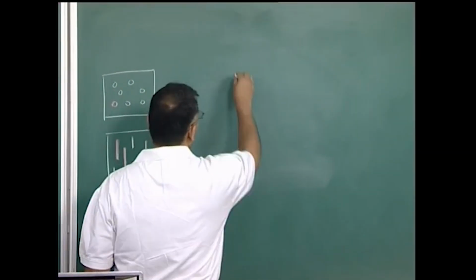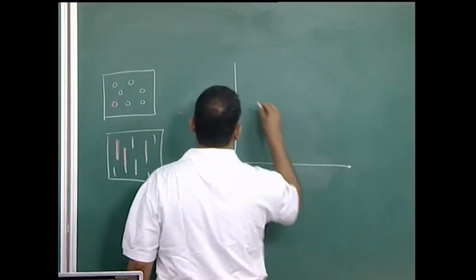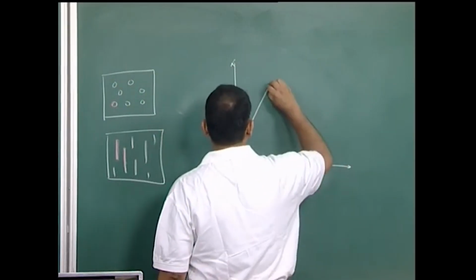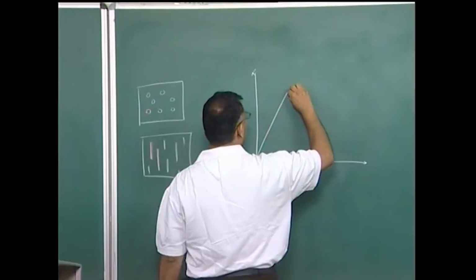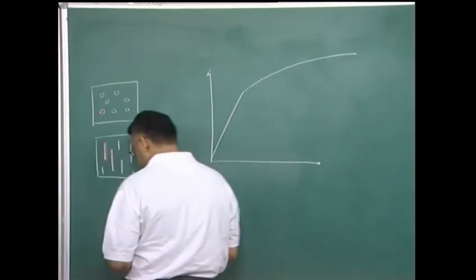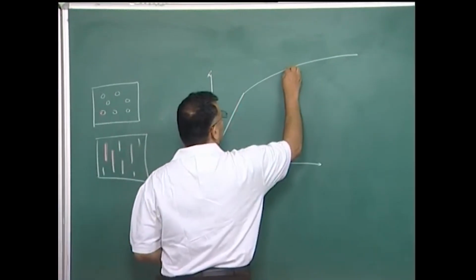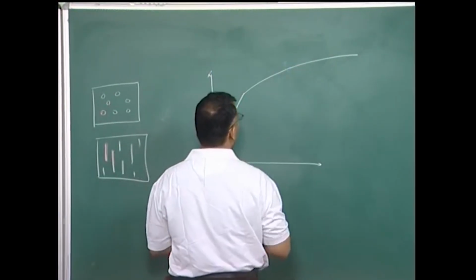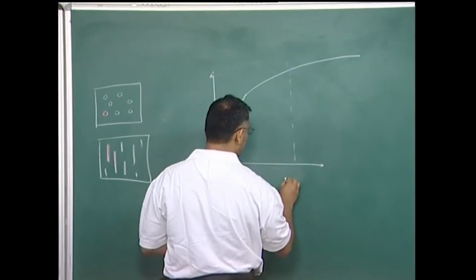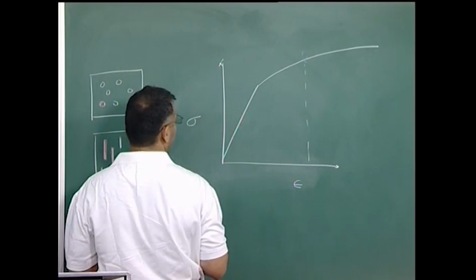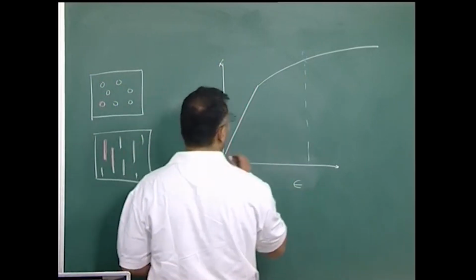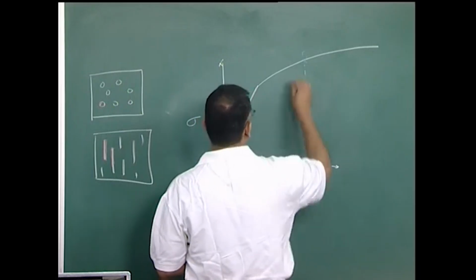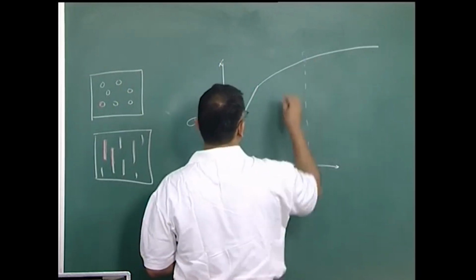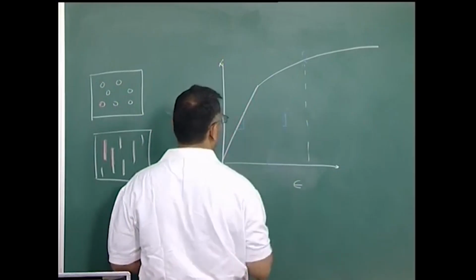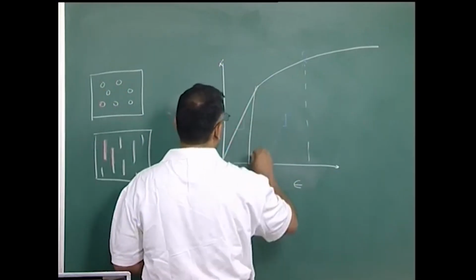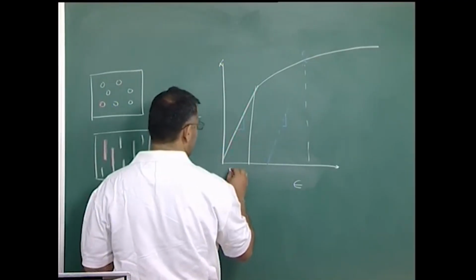So, the elastic deformation I will exaggerate here, so that it becomes easy to visualize the straight region of the curve. This is exaggerated, actually the slopes are of the order of gigapascal. And now, if I unload from a point say m in the curve, then of course, I can draw a vertical line, and this is now my true strain, true stress diagram, and I will now unload from point P, and I will notice that the unloading will take place parallel to this line, the slope of these two lines will be same. And if I notice, then these are two similar triangles, but this implies that